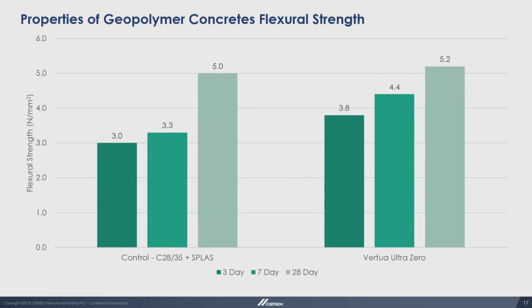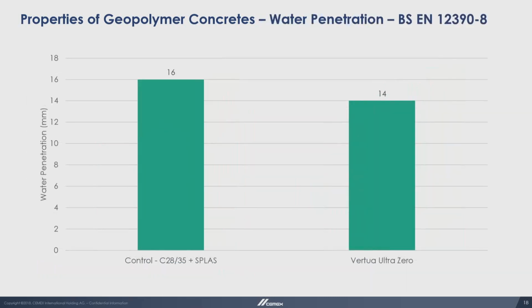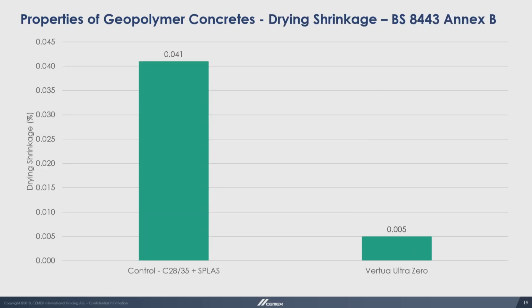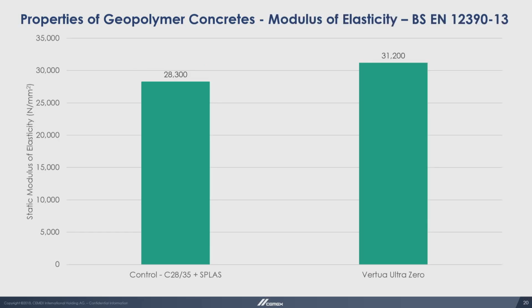Flexural strength, much the same as you would get with standard concretes, perhaps no surprise there. And water penetration, resistance to any penetration of chemicals is good, slightly lower than standard concrete in the test work done on this particular sample. Drying shrinkage is much lower, and again, that's because it's a completely different chemical reaction to cement reaction, and so drying shrinkage is almost negligible. And they're slightly stiffer than normal concretes, given a higher modulus of elasticity.